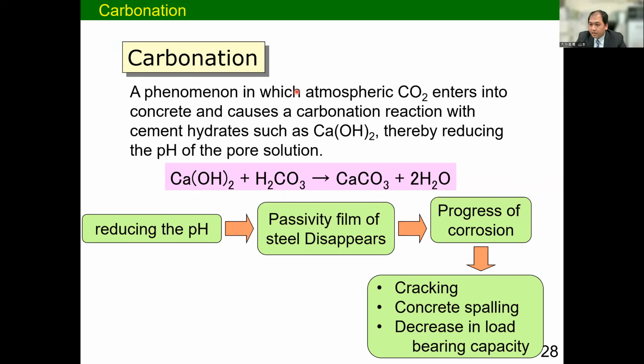First is carbonation. Carbonation is a phenomenon in which atmospheric CO2 enters into concrete and causes a carbonation reaction with cement hydrate, such as Ca(OH)2, thereby reducing the pH of the pore solution. The CO2 in the atmosphere comes into concrete, and then the Ca(OH)2 becomes CaCO3, and the alkalinity of concrete will reduce, and then the passivity film will disappear, and the progress of corrosion starts. Then, due to the corrosion of rebar, cracking, concrete spalling and decrease in load bearing capacity will occur.